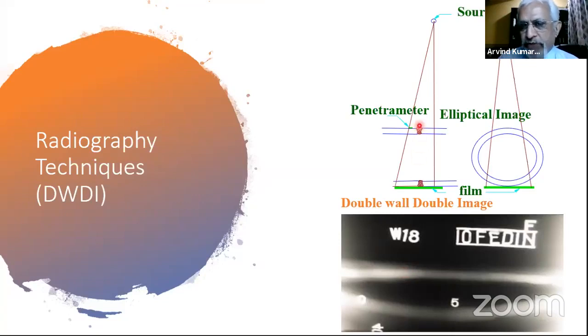What you do is keep the source such that you have the image of both these welds. You can see the bottom weld and the top weld, both are there, but the edges are not clear or do not have a good contrast. So what we do is take one shot and then rotate the source by 90 degrees and take one more shot. When you rotate 90 degrees, you get this image also coming in between and you are able to see the entire weld. So in this case, two images will give you the entire radiograph of the weld. Whereas in other cases, depending upon the diameter and thickness, you may require 3 films, 4 films, 10 films.